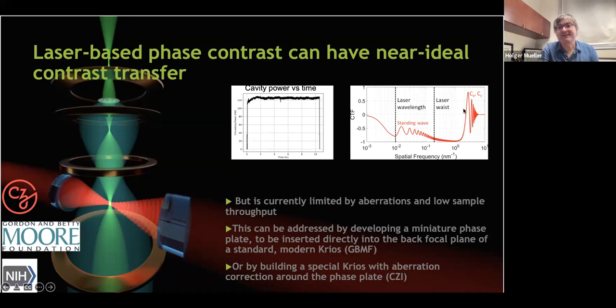On the right-hand side, you see the contrast transfer function. Ideally, we want to see it close to 1 or -1 over all spatial frequencies. And you can see that the contrast transfer function is high over a large range, several orders of magnitude of spatial frequencies, limited at high resolution by the aberrations of the scope. We'll talk about that more later.